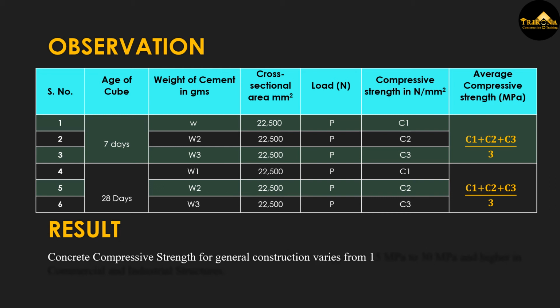Observation. After preparing cubes and placing them for curing, calculate the compressive strength by performing the test for each cube for 7 days and 28 days, repeat the test for another 2 cubes and find the average compressive strength, and note down the values as shown in the tabular column. Result. Concrete compressive strength for general construction varies from 15 MPa to 30 MPa and higher in commercial and industrial structures.